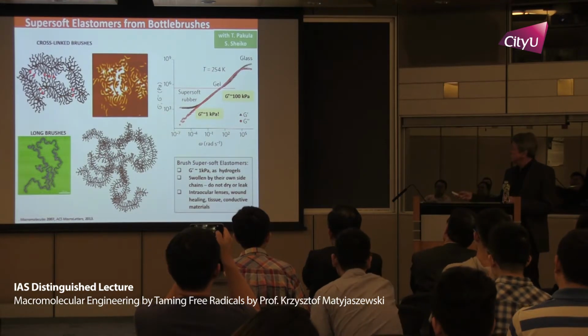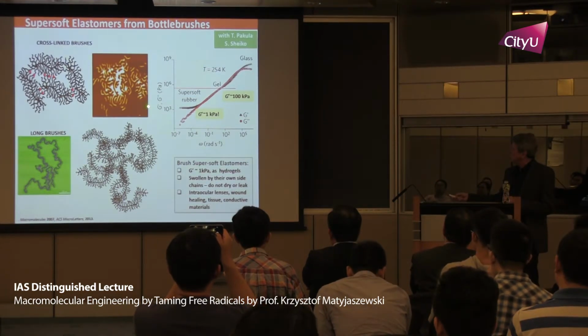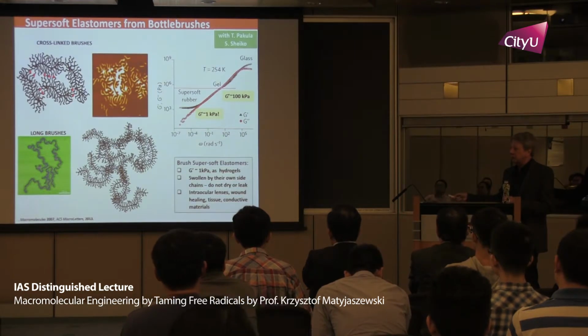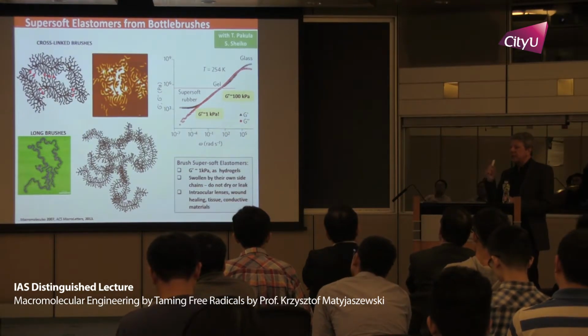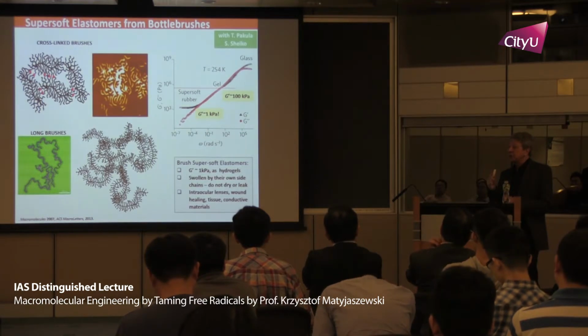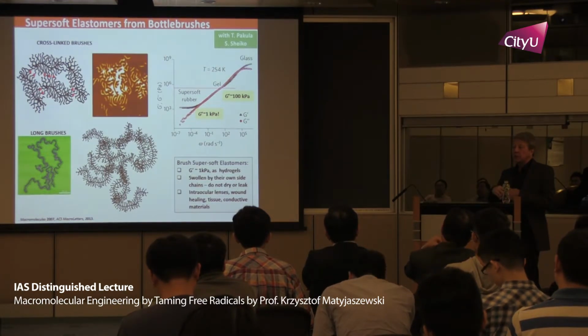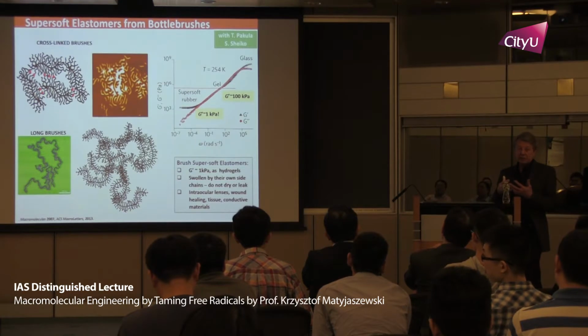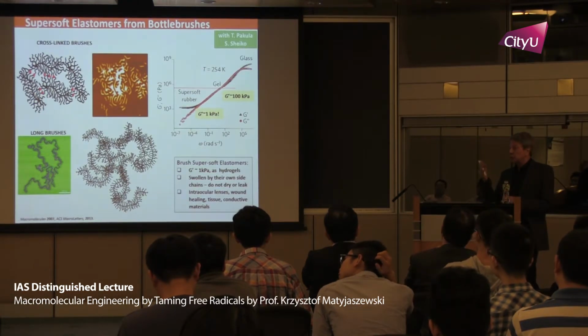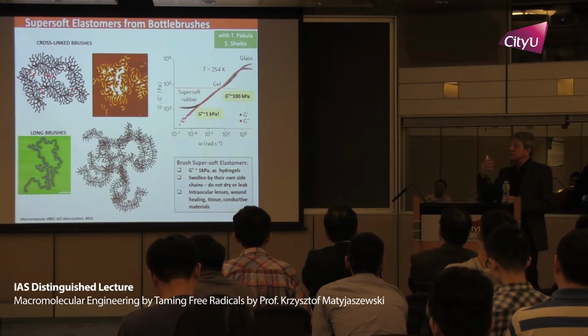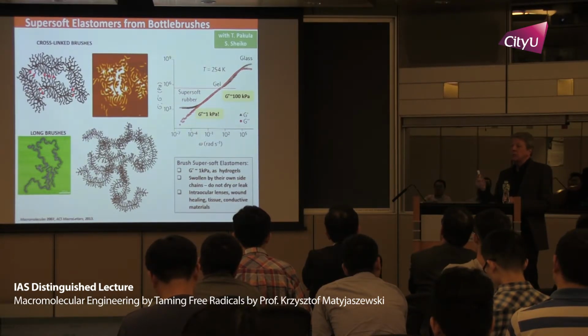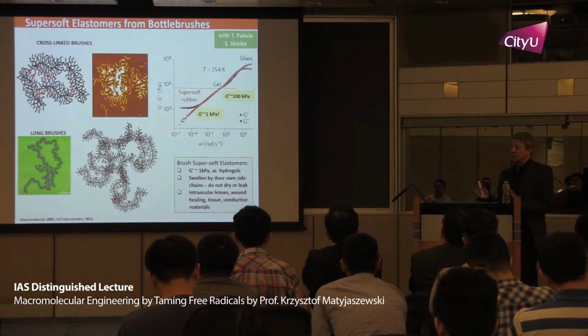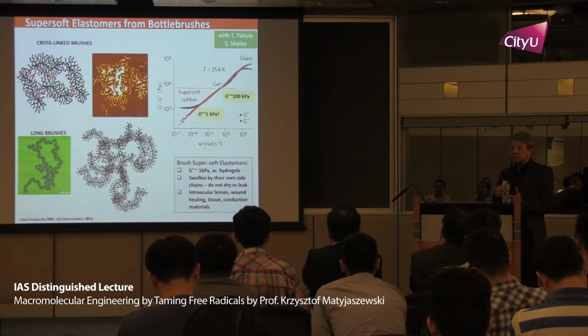So hydrogel is indeed 100 times softer than rubber with a modulus in a range of 1 kilopascal, but hydrogel is 99% water, 1% polymer chain. When water evaporates, hydrogel dries, becomes very hard. If you want to use hydrogels for contact lens, you must expose them constantly to saline solution. So can we make a material like hydrogel which would never dry? It would be a one component material, never dry. How to design material like that?